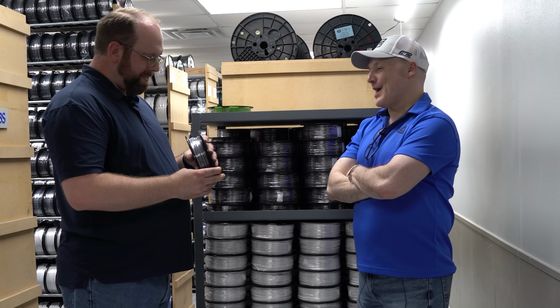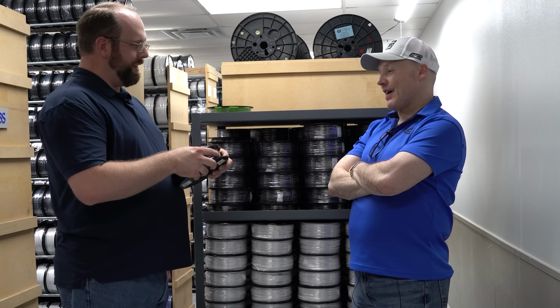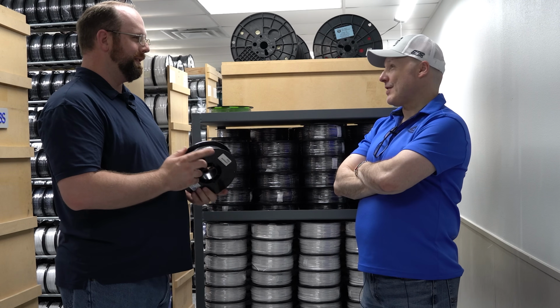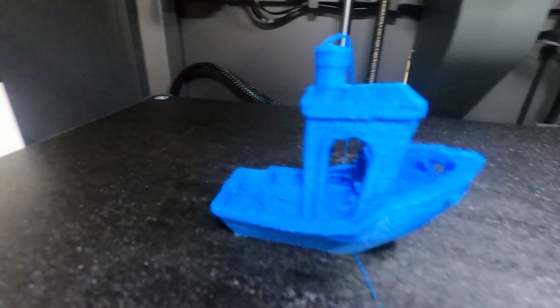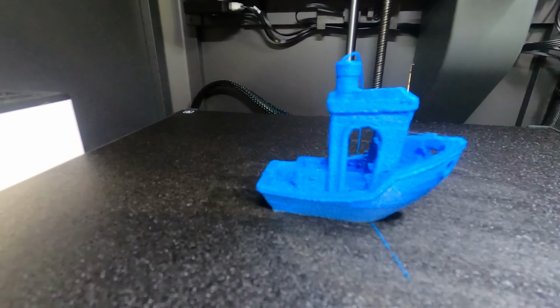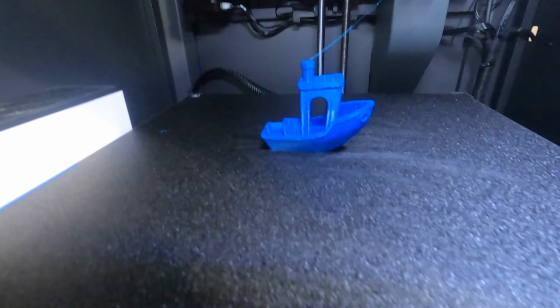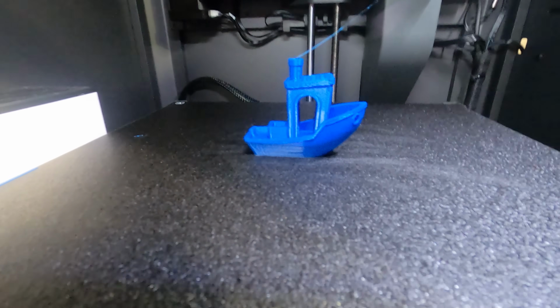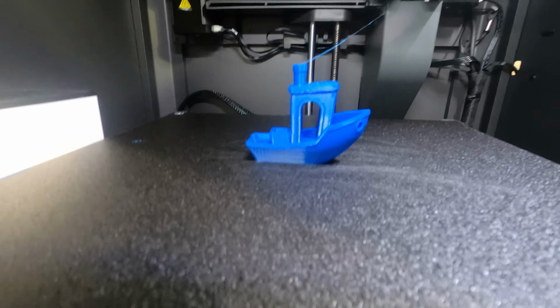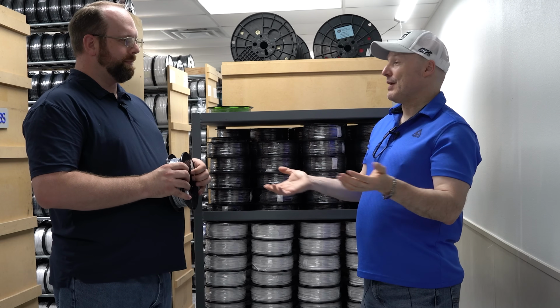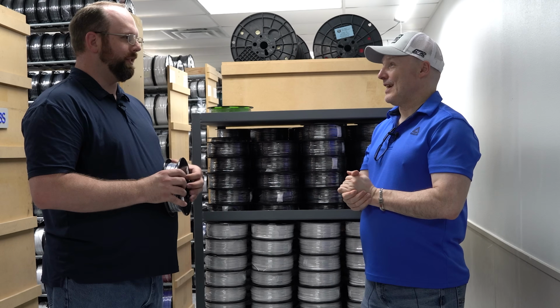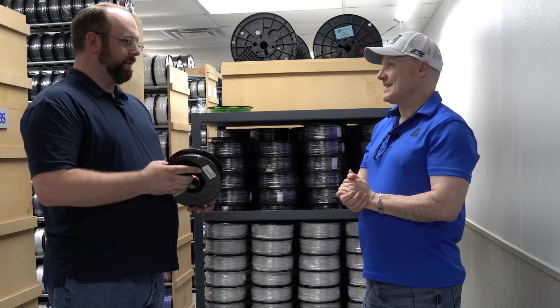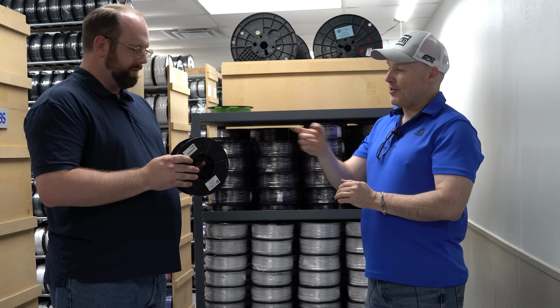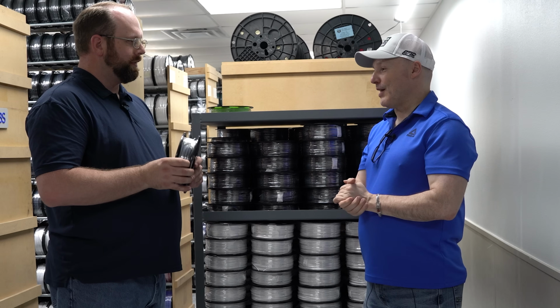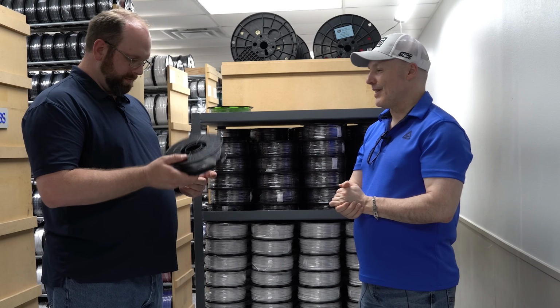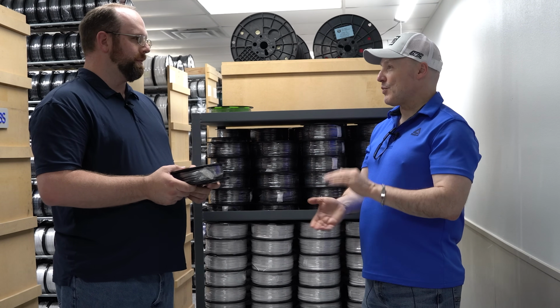So we all know that nylon can be a bugger to work with. I did a video recently where I dried nylon, and what I received was not a vacuum sealed bag. When it was printing, it sounded like I was cooking bacon. It was really bad. But I ran it through the dryer for 12 hours at 70°C, printed it again, and it looked fantastic. I'm not a big nylon printer, but I used default settings, and it came out great for that Benchy. So if you receive a packet of nylon, in your case carbon fiber nylon, what are your recommendations prior to printing with it?